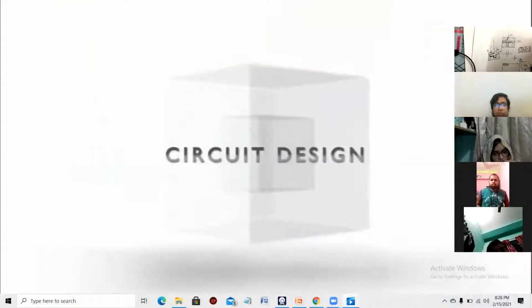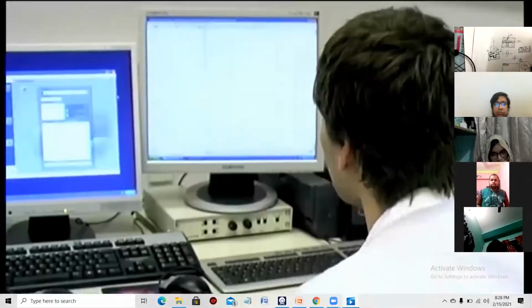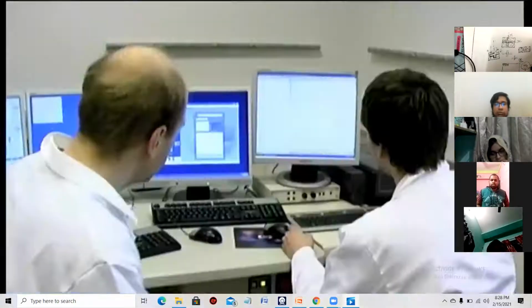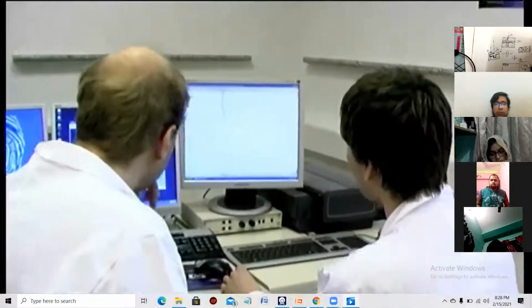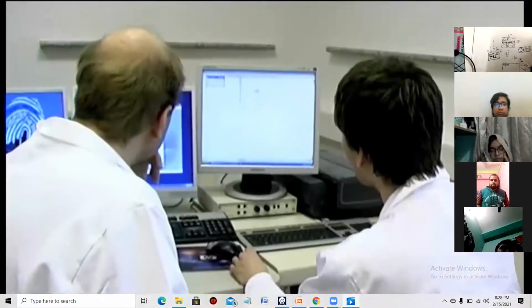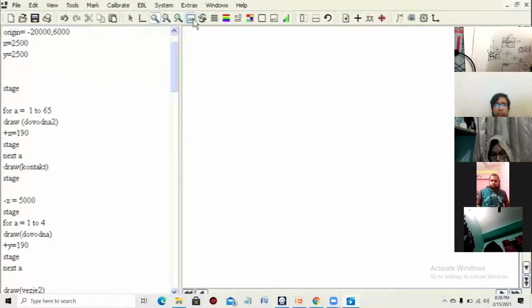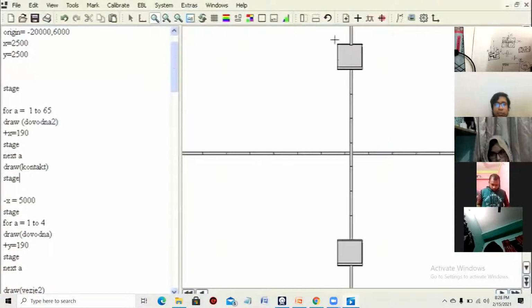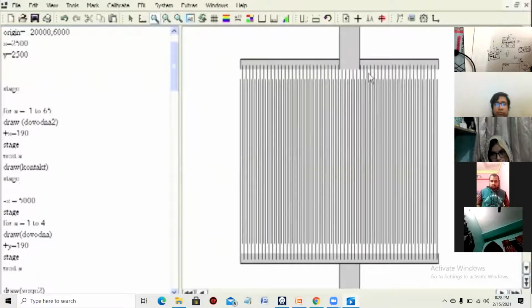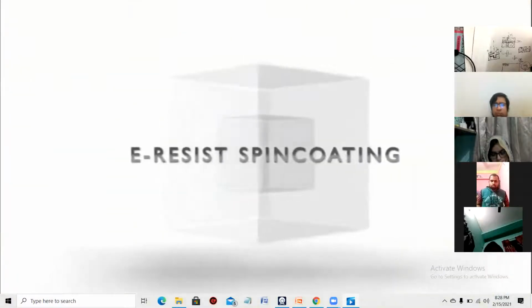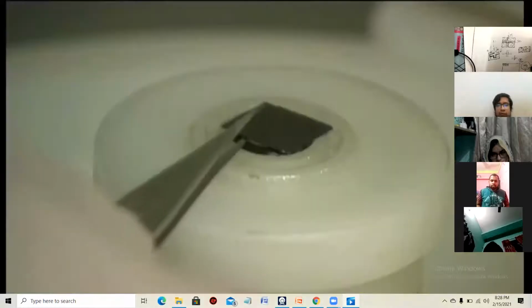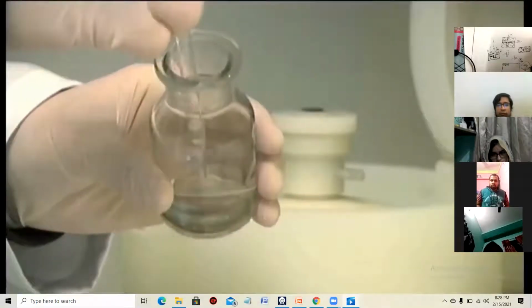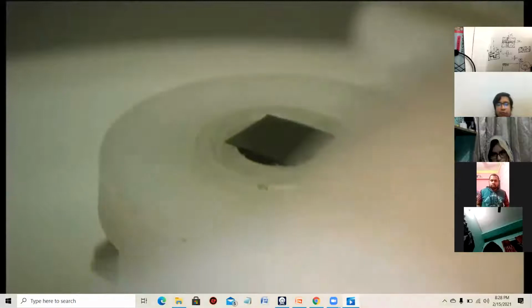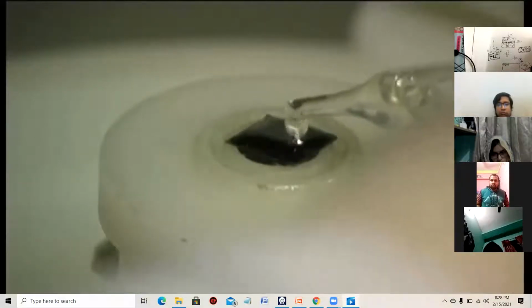The construction process begins with the circuit design, which is quite straightforward through a computer interface. Here we are demonstrating the design of two interdigital electrodes. The whole circuit is 200 micrometers large, with a gap between the electrodes of 500 nanometers. The circuit is made on a silicon plate. The first step is covering the silicon wafer with a thin layer of polymer, which monomerizes when exposed to the electron beam.